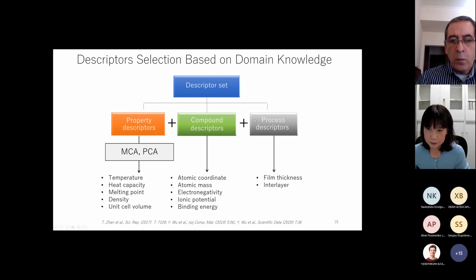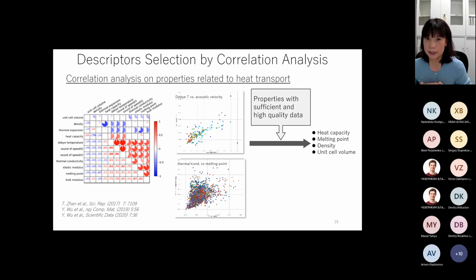Unfortunately, when we collect data from papers, we can seldom find common descriptors for different synthesis methods. And finally, we only find two: film thickness and interlayer. And for the property descriptor selection, there are many properties related to heat transport. Some of them are difficult to obtain, or even if we can obtain them, they have large uncertainty. There is quite a large deviation between different papers.